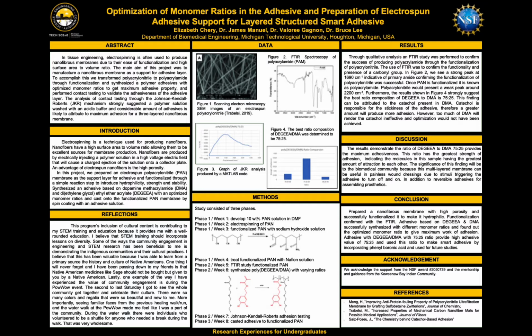So Dr. Manuel and I synthesized 4 batches actually of the adhesive DEGEEA and DMA. Initially, we had synthesized 3, but we stumbled upon an obstacle, and that was that one of the ratios had a very, very low yield, almost to no reaction. So we had to disregard that and add an additional ratio, and that is 75 to 25. So the ratios we had worked with, again, is 75 to 25, and then 80 to 20, and then 70 to 30.